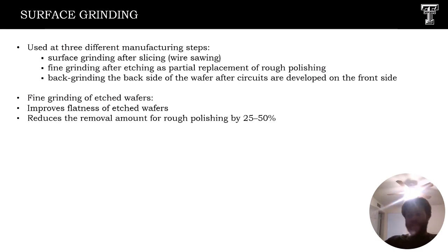And moving on to surface grinding. Surface grinding plays a very key role in wafer production in the sense that it's used at three main stages: after wire sawing to smooth the slices, after etching as a partial replacement for rough polishing, and during back grinding to thin wafers. The best part about this process is fine grinding after etching not only improves flatness, but also reduces the material removal required during polishing by 25 to 50%. That's a very important efficiency boost.